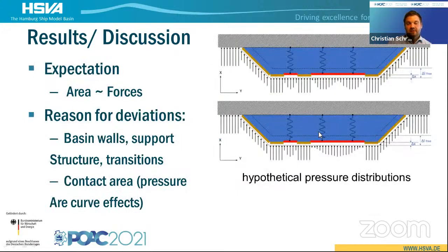If we now come to discussions and ideas why probably the forces are a bit different than we first expected and first thought about. Of course, in the end, what we measure is, we have solid ice before the whole structure. So there will be interactions, of course, with the side walls everywhere around the basin as well. Also with the solid walls, I would just say port and starboard of the test setup, but also with the panels protecting the rest of the measurement setup.